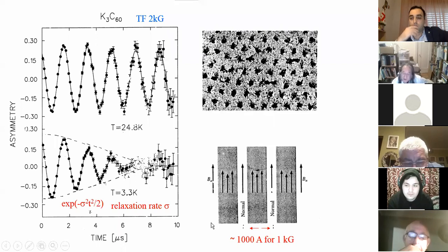But superconductivity has the property of expelling the magnetic field, and it does that in a partial way, so that in the region between the flux vortex cores, you see in between these, the magnetic field is smaller than the applied magnetic field. And what mu-SR is doing is that the first muon may stop here, so it will precess with the magnetic field of this magnitude. The second muon may stop in the core, and then it will precess with a frequency proportional to this larger magnetic field.